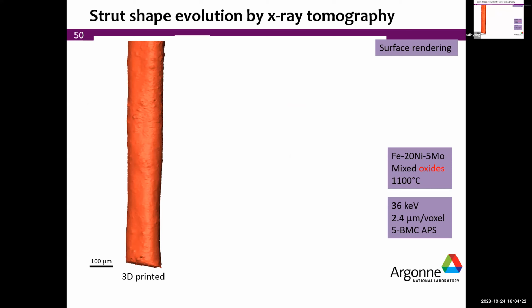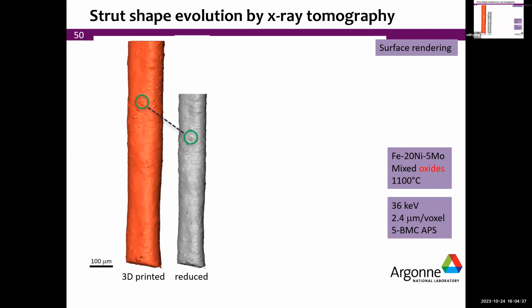So it's about 150 micron in diameter, maybe a millimeter in length. And this is the surface rendering of that material. It is colored red to express the fact that we have an oxide. I want you to also focus on a little defect here just from printing. As we reduce it, there's this huge shrinkage discussed already, but you see all the details here are maintained.